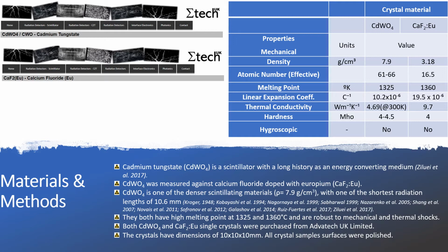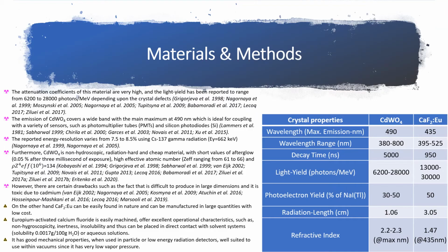Both crystals were purchased from Advatech UK Limited and were in single crystal form. Finally, both crystals have dimensions 10 by 10 by 10 mm and their surfaces were polished. Both crystal properties are shown in the table at the right side of the slide. Cadmium tungstate has a high attenuation coefficient and a wide emission wavelength band with the main maximum at 490 nanometers, which is ideal for coupling with a variety of sensors such as photomultipliers and photodiodes.